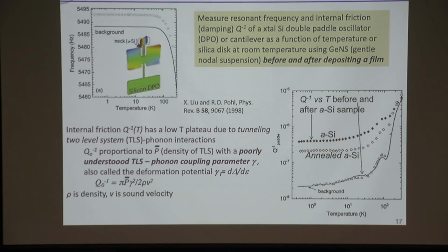And the heat capacity gives you another number. You can get other numbers. There's dielectric losses. We've actually done lots of them. They don't link that well to each other, which is obviously also an indication that it's not well understood. But the heart of what we believe is happening is in that very last slide.